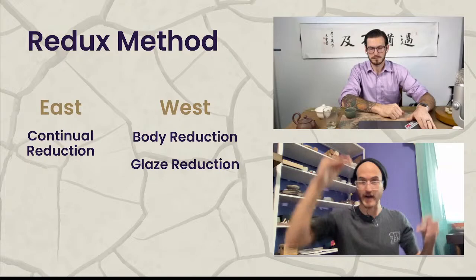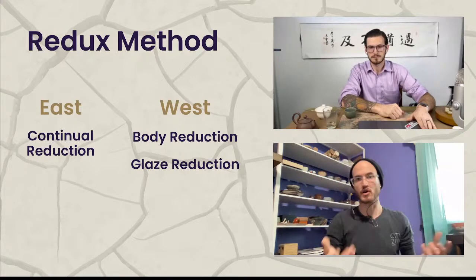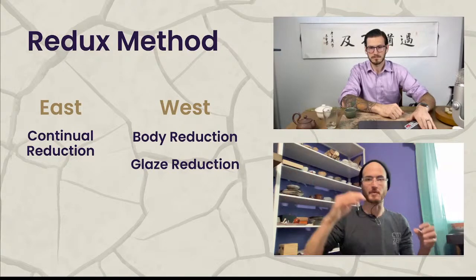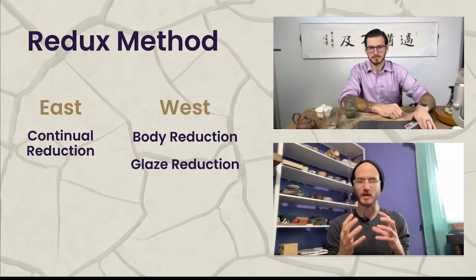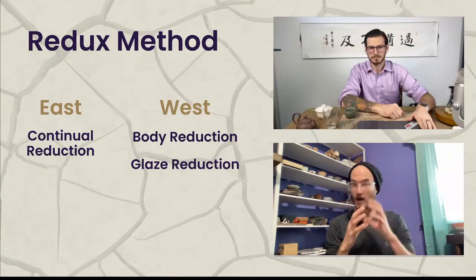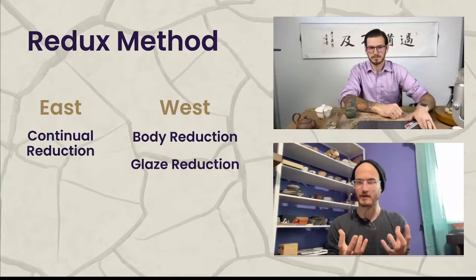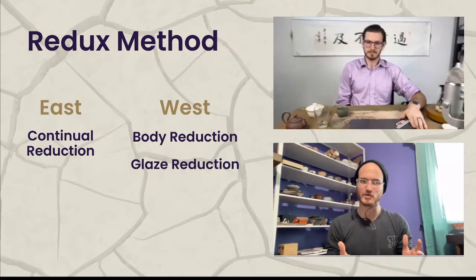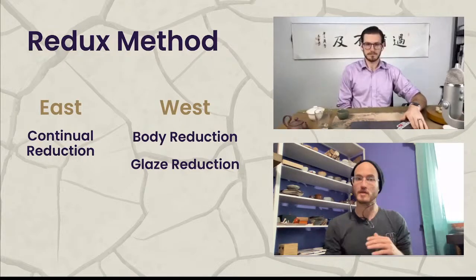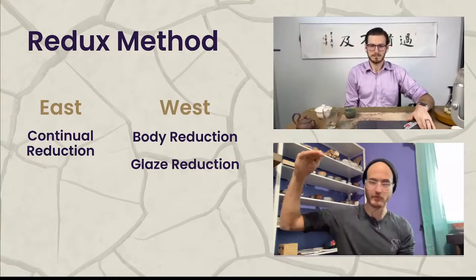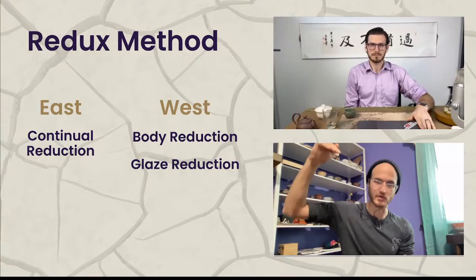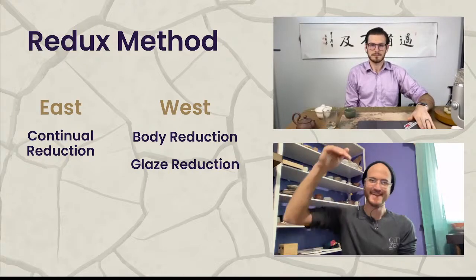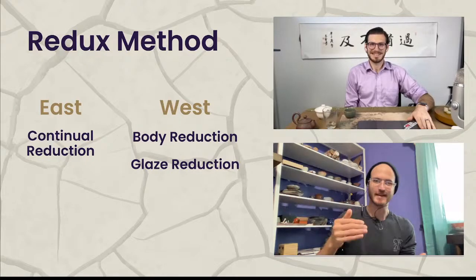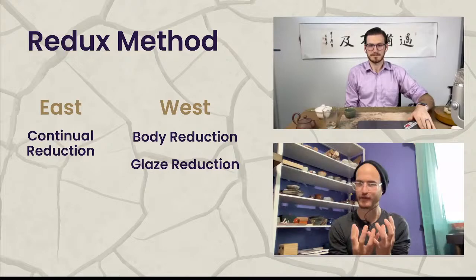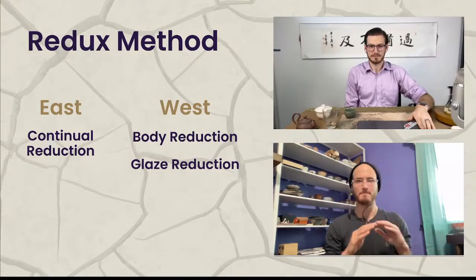So instead of it crashing, which it's still called a crash cool, but instead of just dropping off because you closed it, you're dropping it off with flame in the kiln, and you get all of the surfaces and all of the colors like copper locked in. And the slower cooling also causes a slight matting of the surface, so you don't get so super glossy, which is, you know, some people like super glossy. I don't particularly, so I do like a reduction cool. And you can do the same thing in a gas kiln, put it in heavy reduction at the end of the firing to get a sort of slow drop, crash cool. It's still called a crash cool, down versus a natural cool. So you're crashing it down with some reduction in order to get those sealed off surfaces, really get bright colors and a little bit of matting.